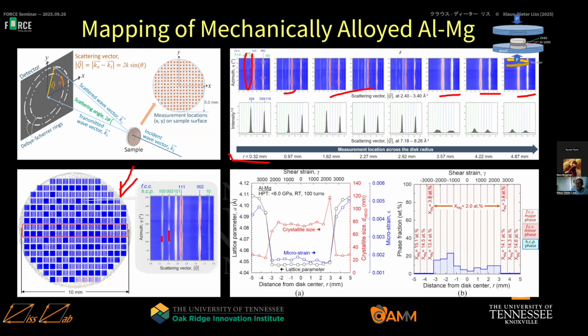So we have a transition region, a transition strain, which we can calculate, a transition radius, where we go from the one to the other. And what happens there is we get an average of 15 atomic percent of magnesium, which we measure here, while in the center, the aluminum only has 2 atomic percent of magnesium. So at the transition radius, we get a lot of solid solution alloying. And it has a very broad distribution, which we can see from the high order reflections here. So we have some grains that have over 40% solid solution, and that's amazing.